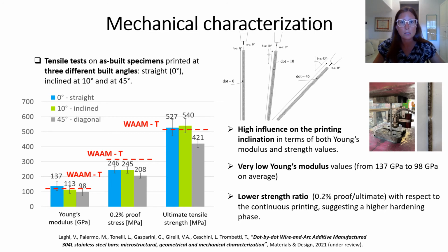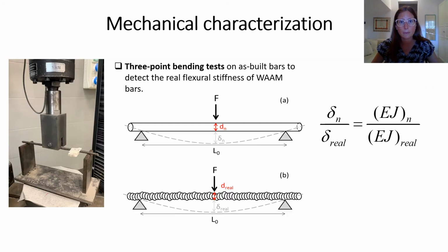The ultimate tensile strength is severely reduced for the 45 degree inclination. And overall, there is a lower strength ratio, which is the ratio between the 0.2 proof stress and the ultimate tensile strength, with respect to the continuous printing, suggesting a higher hardening phase for the dot-by-dot printing.